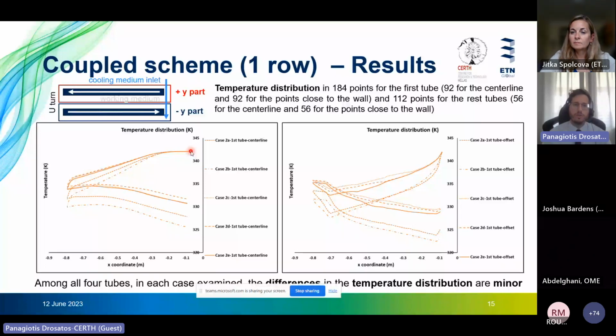Furthermore, the temperature gradient is steeper in the part of the tube formations which are closer to the cooling medium inlet, because in this specific zone lower absolute temperature values of the cooling medium are experienced, so higher wall heat transfer coefficients can be developed.